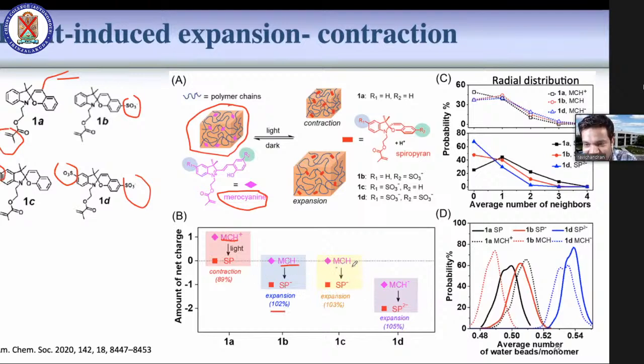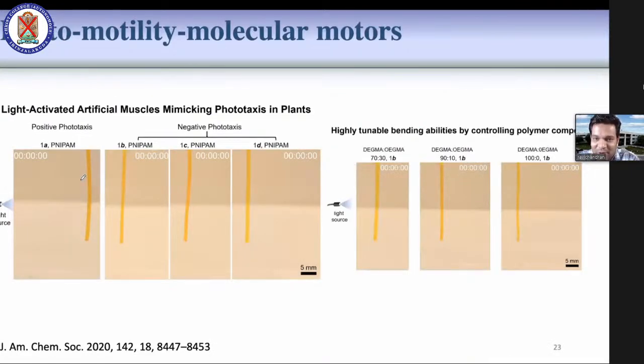And when you have merocyanine negative, the expansion is 103%, and with merocyanine to SP negative 2, it expands to 105%. That can be tuned, depending on the structure and the charge substituted in the backbone of the spiropyran. So how does cross-linking work? You engineer the material, the real cross-linking gel.